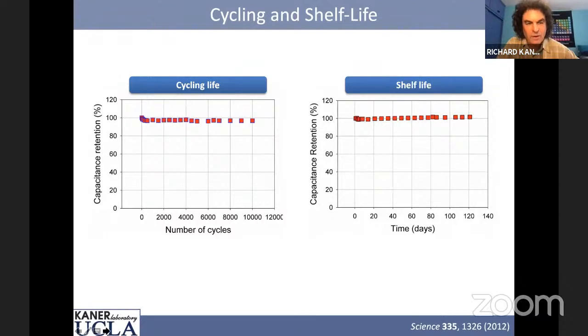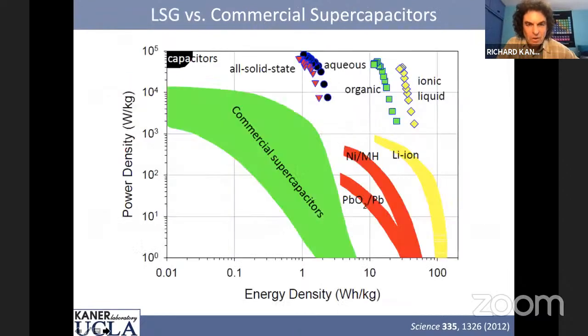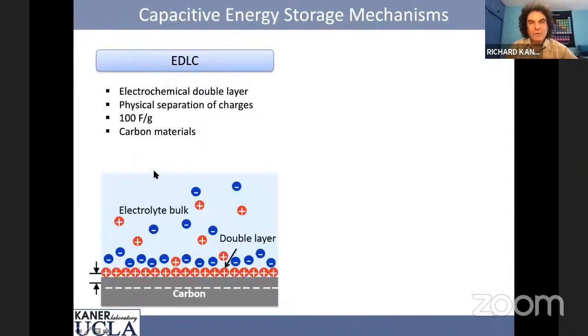So then you may say, okay, well, what do we need to do? Well, if we actually look at this Ragone plot, power density versus energy density, here are commercial supercapacitors. So they're considerably better than that. Here's our aqueous devices, our solid state devices, organic and ionic liquid. But if you compare them, they're comparable, let's say, to lead acid batteries as far as energy storage, but they're nowhere near lithium ion batteries. So if you really want to use these for energy storage, what you really need is either to combine them with batteries, which is one approach, but probably a better approach is to make hybrid devices that start to approach lithium ion materials. And the question is, how do we do that?